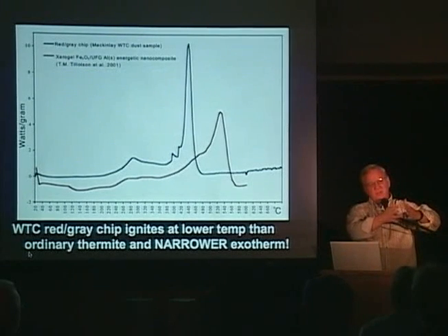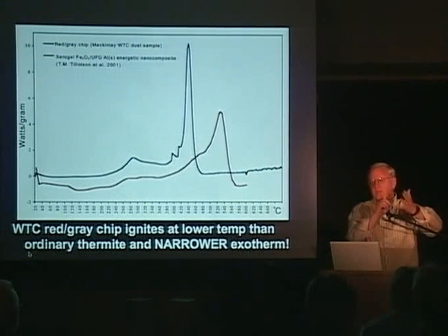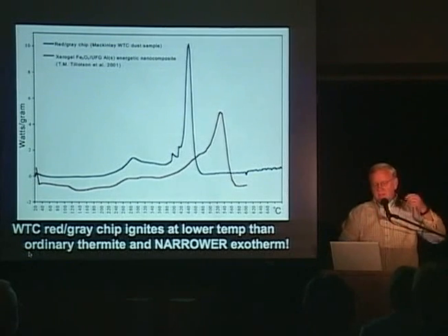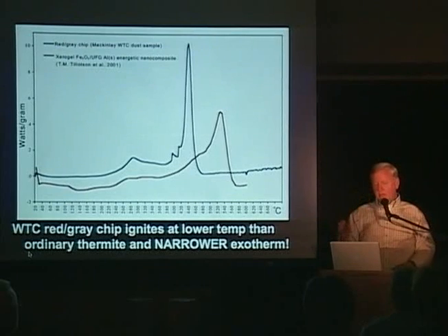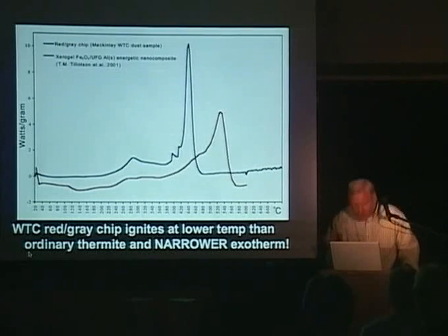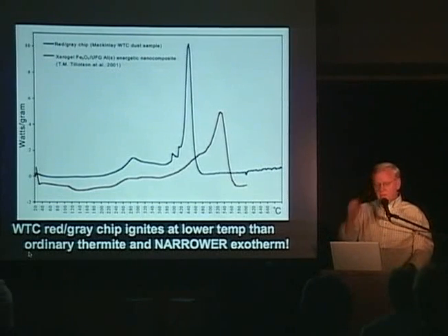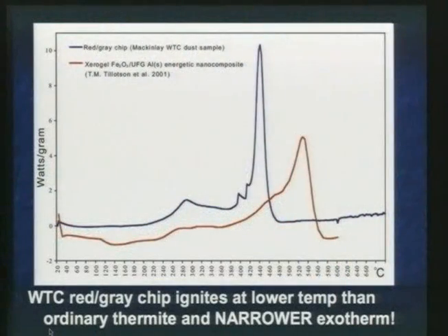So you heat this material, any test material, slowly. In this case, we use their conditions, 10 degrees centigrade per minute in air, and you heat it up, and in their case, the nanothermite, they made it, they know what it is, that's the red curve, goes off at just about 500 centigrade. And the peak there is actually quite narrow compared to regular thermite. It's also at a lower temperature. I'll show you that in a minute. This is the way we can distinguish nanothermite another way from regular thermite.